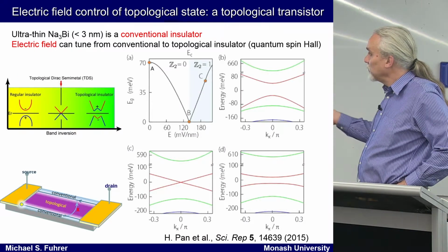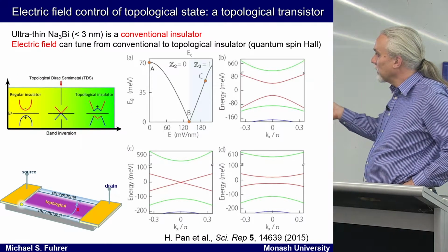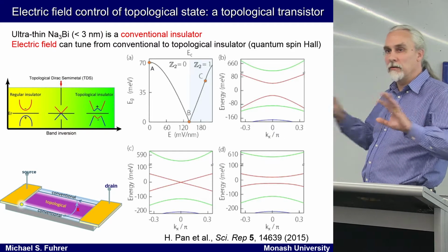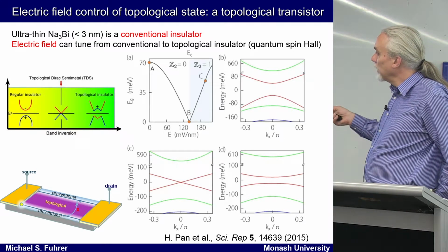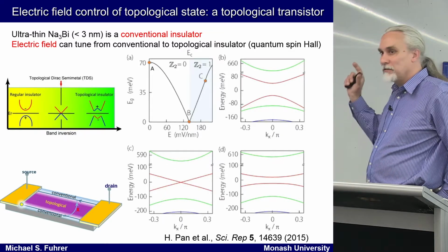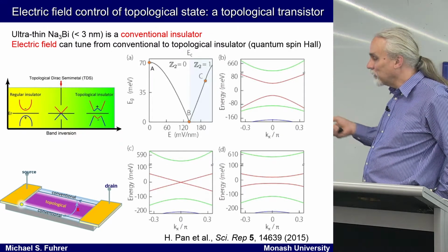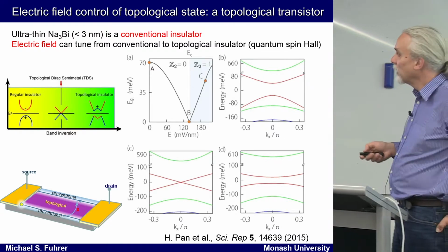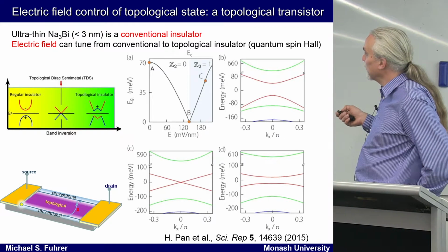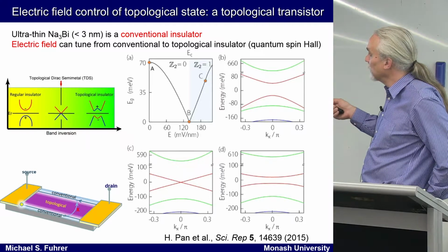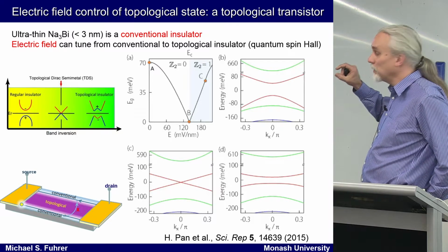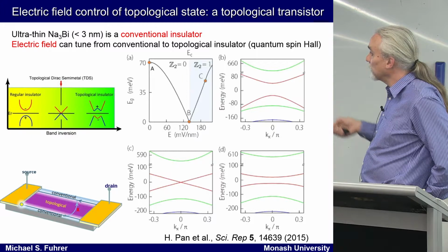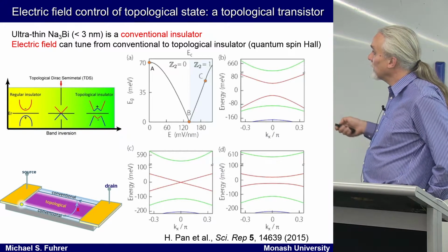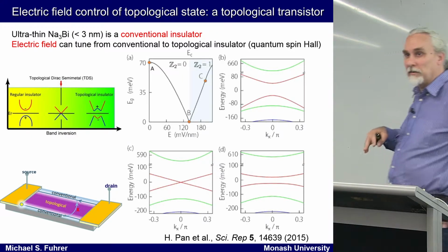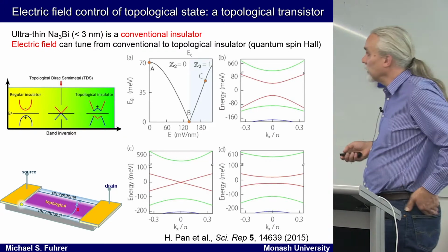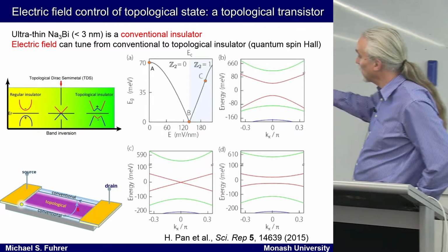So that's rather nice, because if we have this topological Dirac semimetal, we can perturb it, push it one direction or another, and create either a topological insulator, which has dissipationless edge modes, or a conventional insulator, which is insulating. And there are examples of this, at least in theory. So for instance, if I take sodium-3 bismuth and I make it very thin, I can turn it into a conventional insulator just by confinement. And then if I apply an electric field, I can change that conventional insulator to topological, and it'll go through this semimetal phase in between.